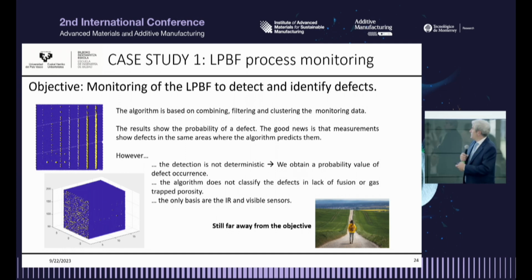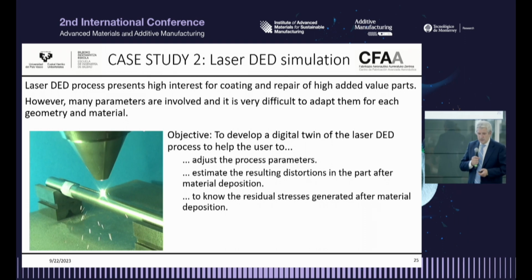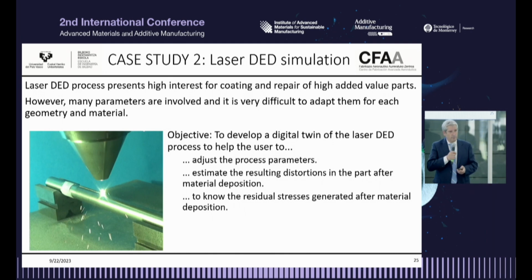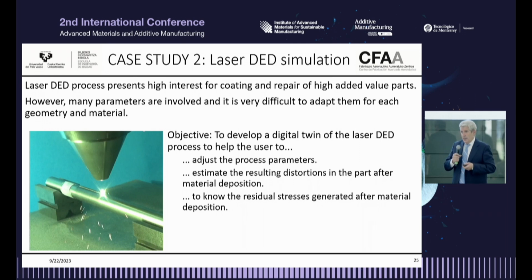And in the second case, this is for direct energy deposition. This process is very interesting for coating and repair of high added value parts. The idea is to deposit material on previous parts, but here, one of the characteristics is that we have to make it good the first time. We cannot test because we are repairing a specific part with a lot of added value. For example, a blisk, which is 60,000 euros or dollars, and we cannot test. The part is what we have. So we have to make it good the first time.